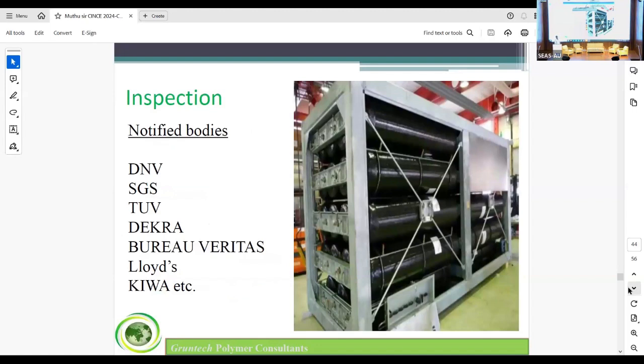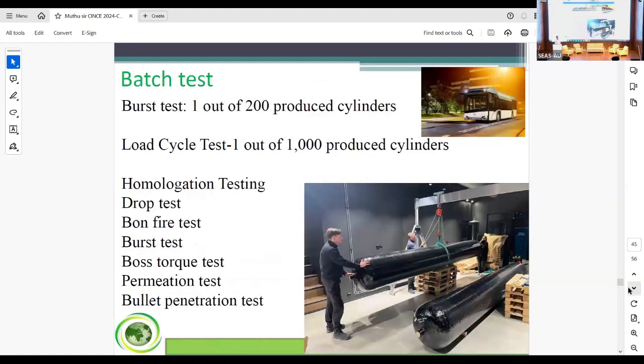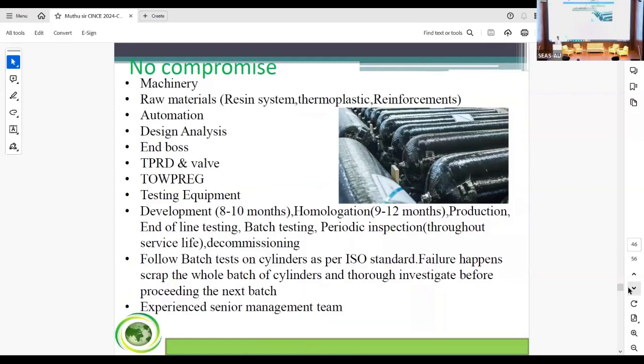So you can approach them before you prepare the design and everything, to have it for the test and approval. Batch test: one out of 200 produced cylinders, one burst test. From that batch, one cylinder will be tested for burst. A cyclic test, a fatigue test, you can say: 1 out of 1,000 produced cylinders, one cylinder will be taken away and tested. So homologation, these are the procedures: homologation testing, drop test, bonfire, burst test, torque test, permeation, bullet penetration.